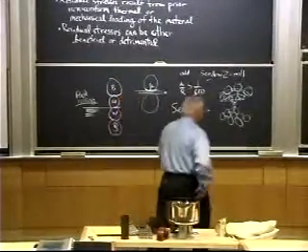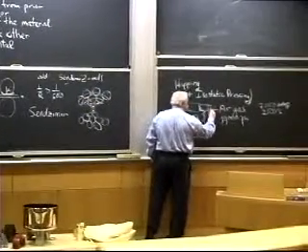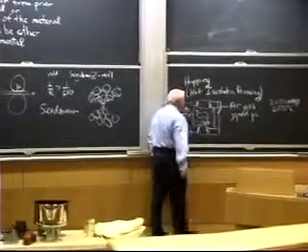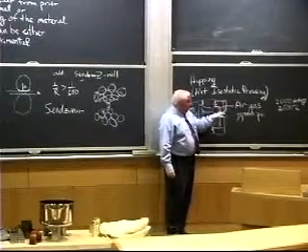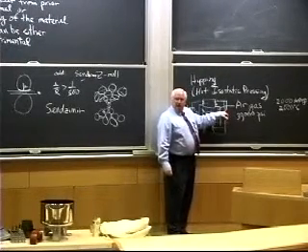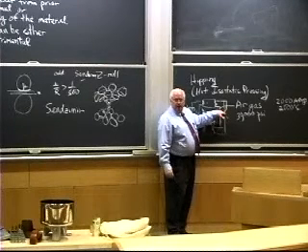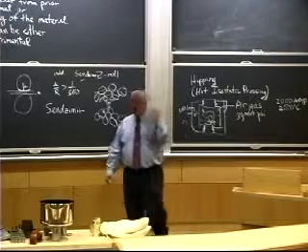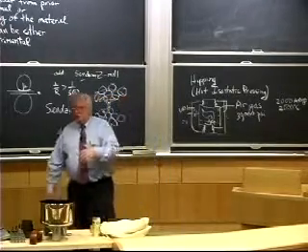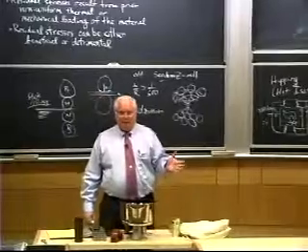It had a little stress concentration on the outside wall. It had a change in shape here. They made it a little bit thicker because of the threaded connection here, and it had a change in section. They had a fatigue crack grow right there, and it grew to only about 5/8 of an inch in size. So you go through the fracture mechanics on this. It turns out that the material didn't have the proper toughness from the steel mill.